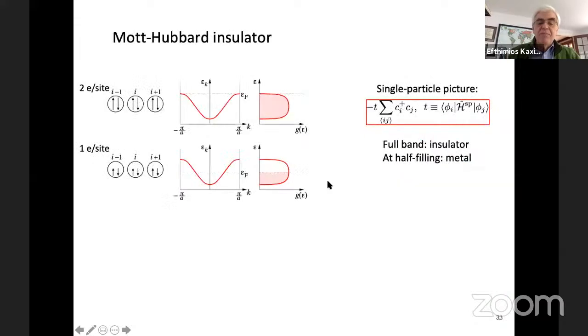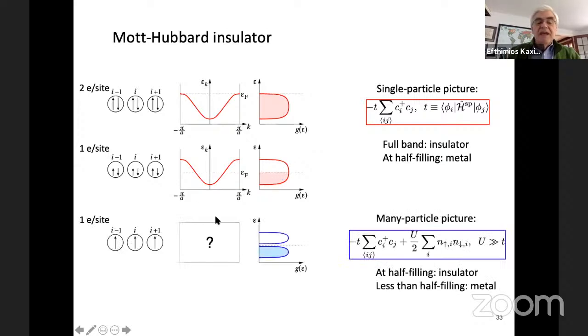Now, this is very peculiar behavior. If you have a single band and it's completely filled, that's the density of states as a function of the energy, and a filled band would correspond to something like that. A half-filled band would correspond to something like that, but no gap. In order to get a gap, you have to have behavior different than the one that I was describing before. You have to have correlated electrons.